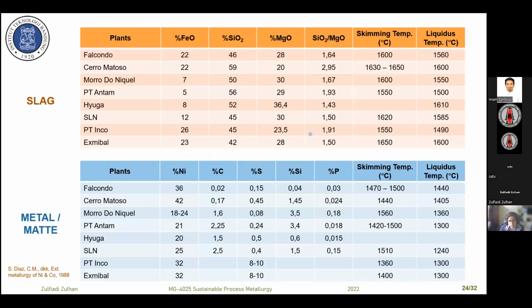And this is some of the operating data from some plants in the world, the iron oxide content. This is for high nickel content. You see here, if you have high iron oxide in the slag, you have high nickel content in the metal, which means also less iron content in the metal. And in these two cases, we have a little bit less nickel content, around 18-20% nickel, and we have high iron content in the metal, low iron content in the slag.